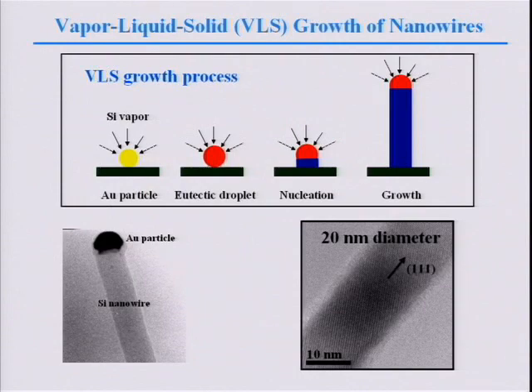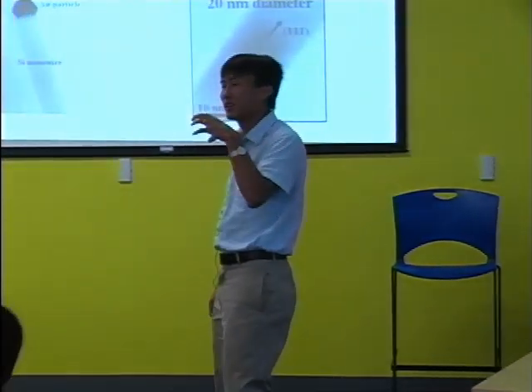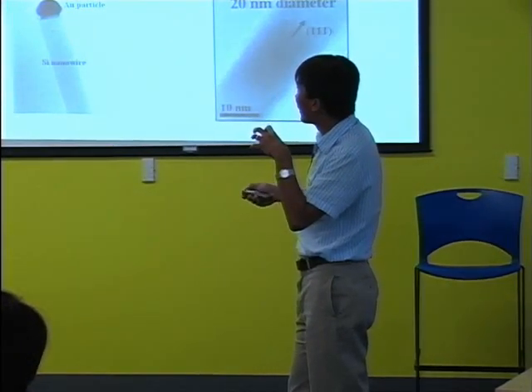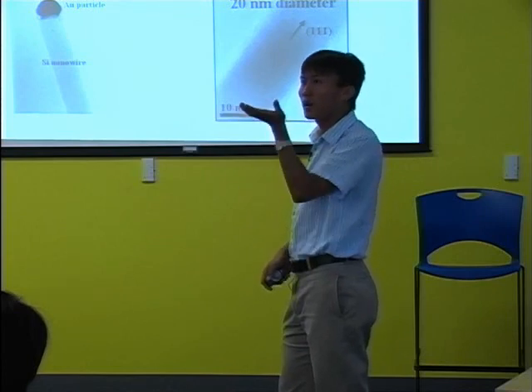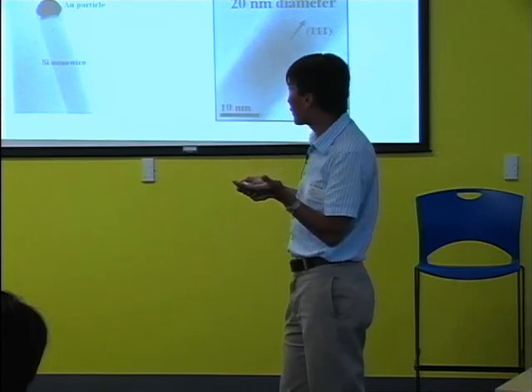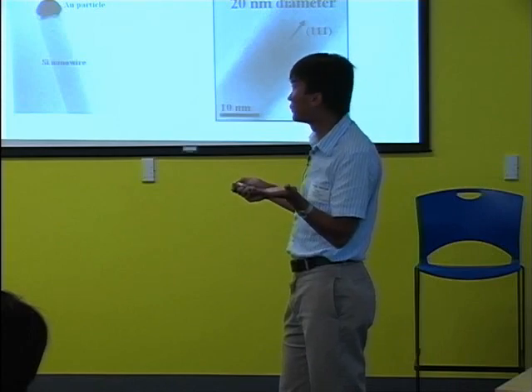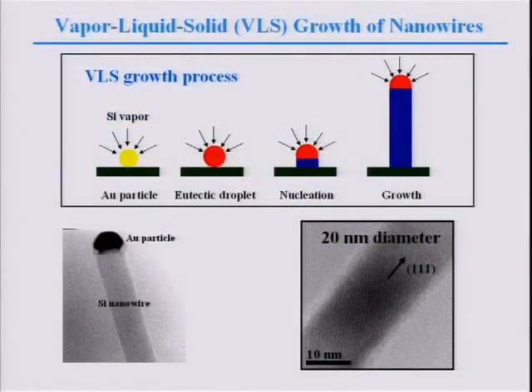Now, one more type of nanostructure produced by chemical synthesis, by a bottom-up approach, is semiconductor nanowires. There are many ways to make one-dimensional nanowires. One particularly powerful way I have been working on is the so-called vapor-liquid-solid growth of nanowires. It comes from the idea that you can take tiny, nanoscale seed particles that function as a catalyst. For example, if you want to grow silicon nanowires, you can take gold nanoparticles and heat them up above, say, 400 degrees C, and pass silicon precursors, which could be silane. These precursors decompose and deposit into the gold nanoparticles.